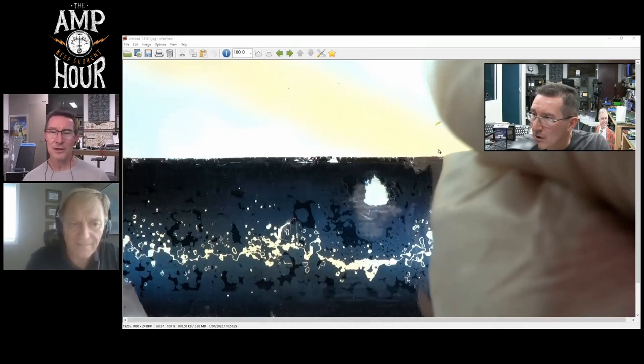And is that something you can test after you've constructed them? Yes, that's a very good point. So how do you do that? What we could do, we'd put them on a moisture humidity test. Maybe 40 degrees C and 40% RH, and maybe another at 40 degrees C and 80% relative humidity, and then do an 85-85 cell. And what we would look at is the degradation of capacitance across time, and that would tell us a lot of things about what's happening within the device.